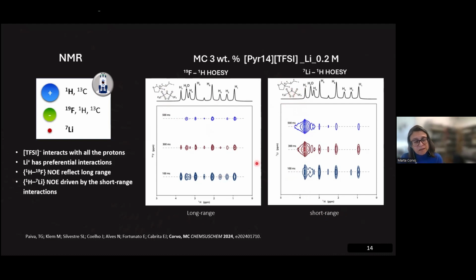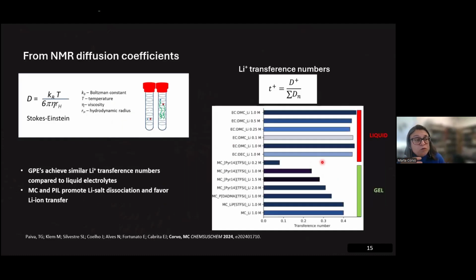And from the interpretation of both of these spectra, you can see that, of course, the bis(trifluoromethanesulfonyl)imide is interacting with all the protons in our samples. Lithium in here is showing preferential interactions, and by judging these long and short range interactions, we can evaluate how the association is taking place. And the most interesting part comes later when we look not only at this part, but also at the way that things move inside the sample.